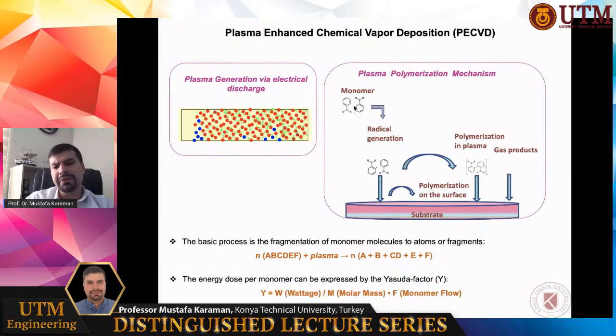In ICVD, the monomer molecules are never dissociated, never fragmented, and they reach the surface without fragmentation, and the monomer functionality fully remains in the as-deposited polymers. But here in PECVD, some level of functionality loss is always observed. In our research, we want to keep it as low as possible. So to achieve this, we need to have low energy per molecule. The energy dose per monomer, which can be expressed by the Yasuda factor, can be kept as low as possible to prevent undesired monomer fragmentation.